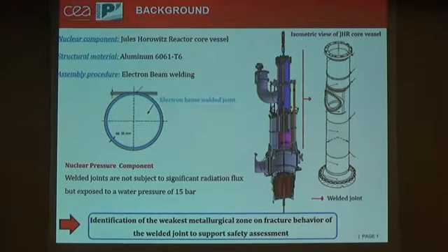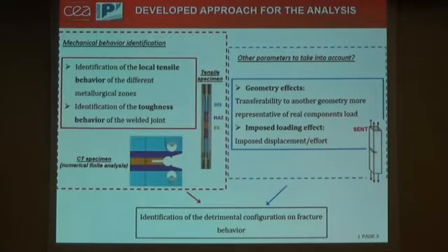And hence the importance of the identification of the weakest metallurgical zone of fracture behavior of the welded joint to support safety assessment. For such demonstration, some experiments and numerical analysis are required, and the strategy adopted is summed up in two main points. First of all, the identification of the local tensile behavior along the welded joints, and secondly, the identification of the toughness behavior of the different metallurgical zones. But with this, there are other parameters that must be taken into account, such as the geometry effect and the imposed loading mode that may have an impact on the analysis of the test results.